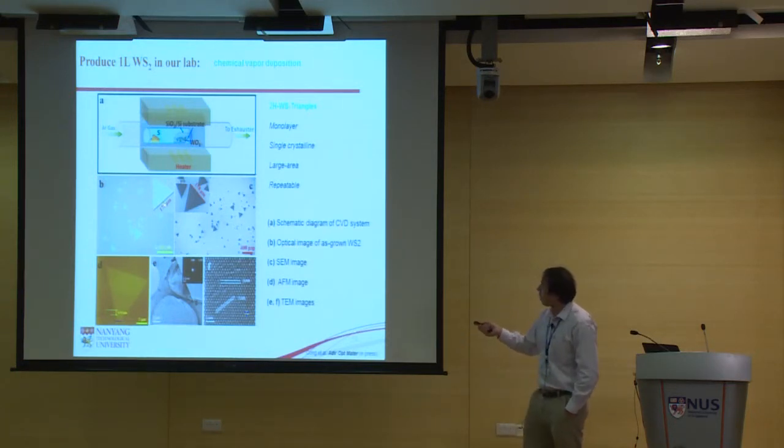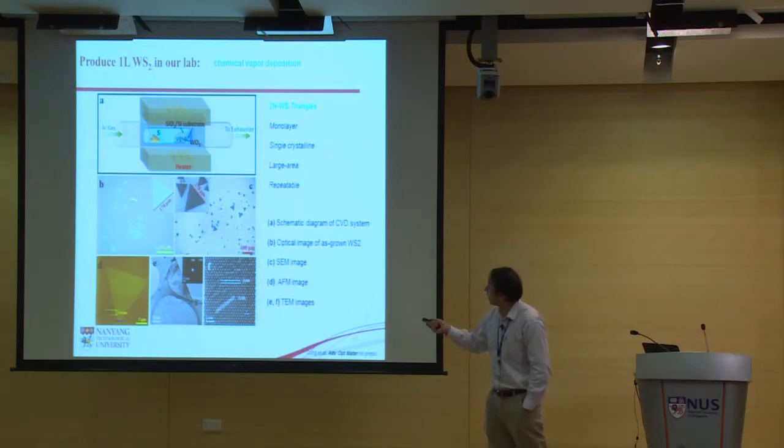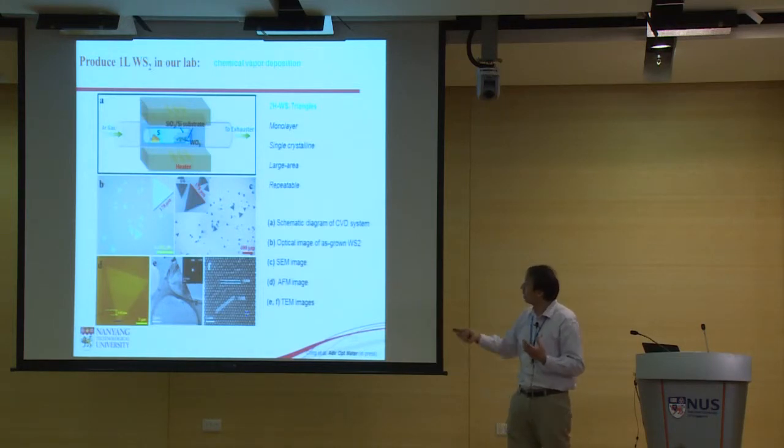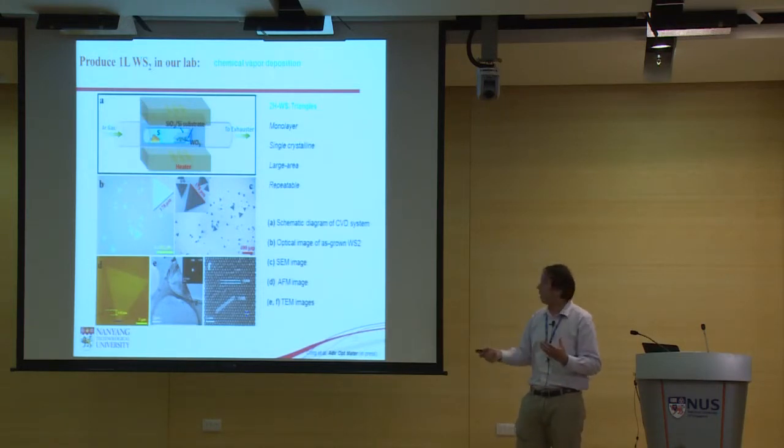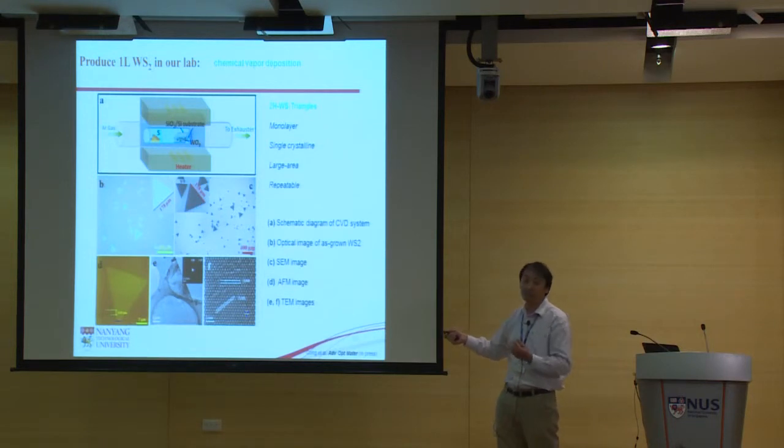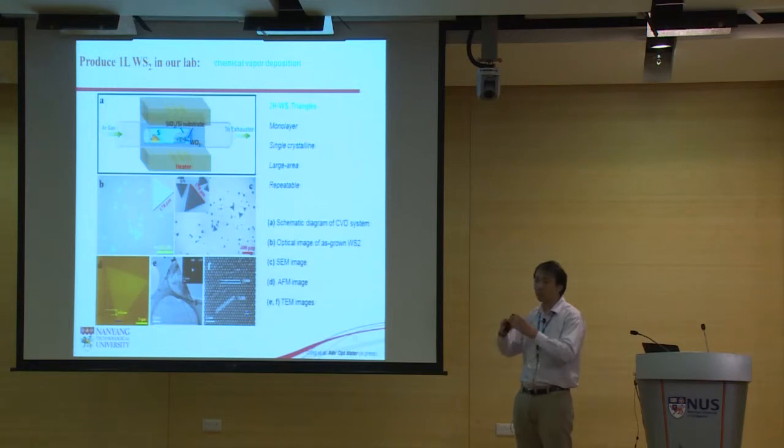Here we have the optical image, which shows many pieces, but obviously we don't really have control. The dimension, you can see, ranges from, say, 170 micron to some tens of microns. And so far, the largest piece we have is this perfect triangle. It is really large, more than 200 micron, though they cannot all be perfect triangles. You will see some distortion, curvature of the edge.